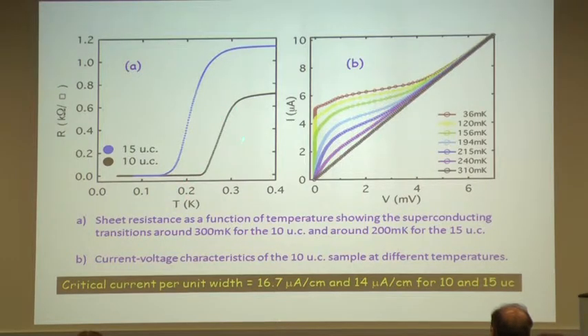If I blow up this area, you have a very clear superconducting transition, with an onset at about 0.3K, slightly lower here. If I measure the current versus voltage characteristics, when I'm sitting at 310 millikelvin, I have a perfectly ohmic behavior, which tells me that I'm in the normal state. And as I cool it down to lower and lower temperatures, I start seeing a well-defined critical current. That's a clear signature that I'm dealing with robust superconductivity in this material.